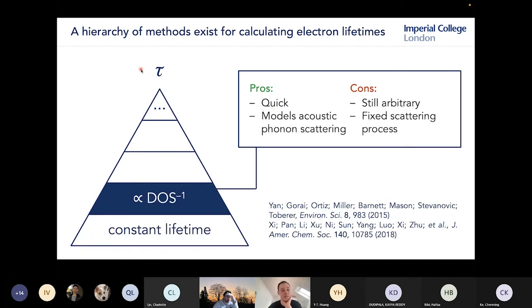So we can do a little bit better than this, by using approaches which try to model physical scattering mechanisms. One of these is called the inverse density of states approximation. The idea is that you set the amount of scattering proportional to the size of the density of states, which is just saying that if you have more states to scatter into, you'll have more scattering. And so this again has the benefit that it's very quick, and it models an actual physical scattering process. So this is acoustic phonon scattering.